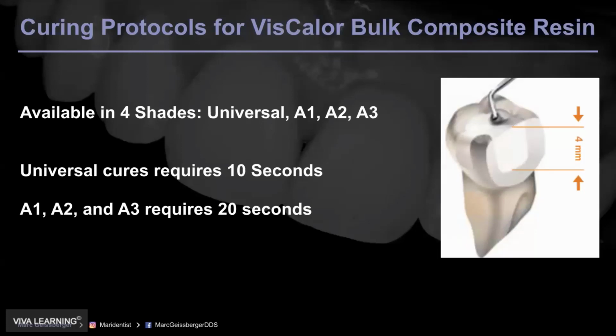And I think what happens, and the reason we see so many issues with this technique of bulk fills, is number one, the composite may be undercured, not because of the product itself, but because the clinician failed to recognize the need to measure that depth. That's reason number one. Reason number two would be actually improper curing with a light that may not be functioning properly. And I will touch on that in just a bit. So I think it's important to recognize that you need that to ensure that you've got that 4 millimeters.